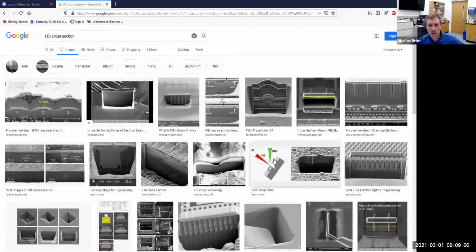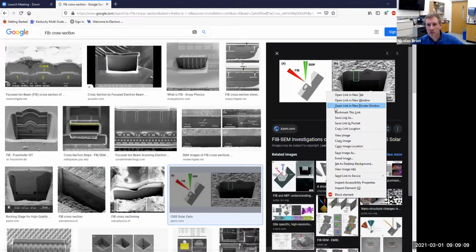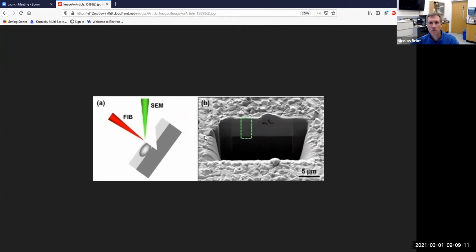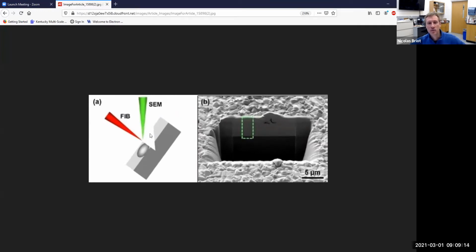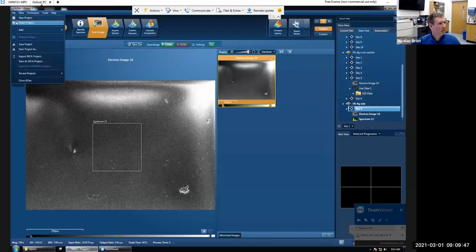So what I did on it is a FIB cross section. That's where you tilt your sample and you have a focused ion beam in the machine and you start cutting perpendicular to your surface. And then the SEM can image that cross section, and not just image, but also generate X-rays. So you can do EDS on the cross section. Okay. So my thought was to do a line scan on the cross section, and because you don't involve physical cutting and grinding, maybe you can capture the first few microns a little better. So let me open those results.